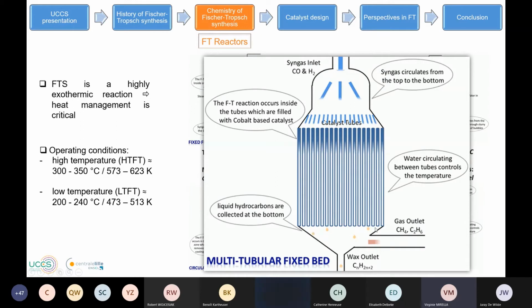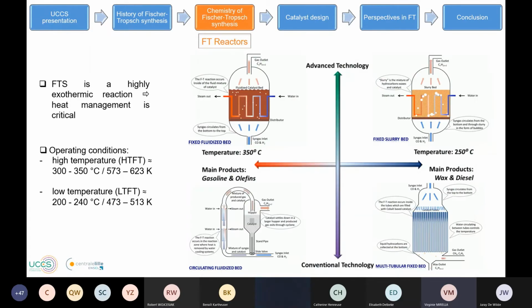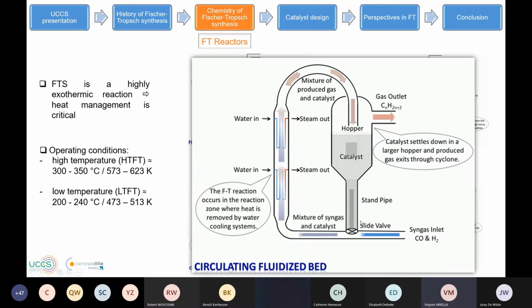And the liquid goes through the bottom of the reactor, and we have another exit for the light gas molecules. Then we also have the circulating fluidized bed reactor, where the catalyst is doing a loop. It comes with the syngas, the catalyst, then we have the water as cooling agent, it reacts, and then we have the exit of the lighter gas molecules, and the catalyst goes through a cylinder to be recovered and continue this loop for the reaction.